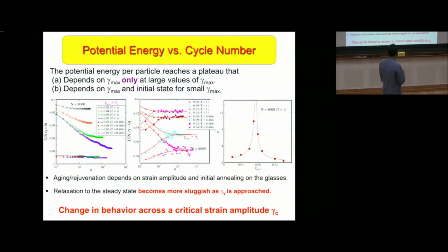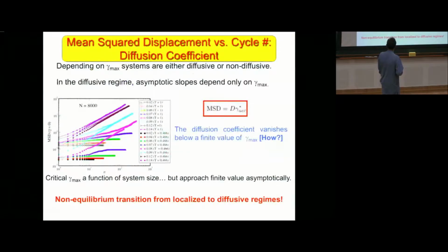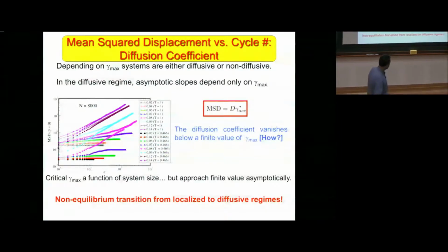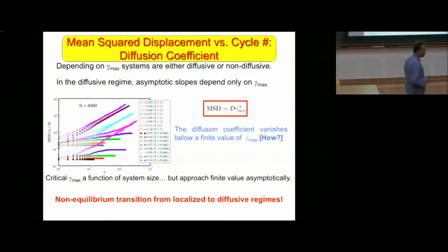And what you also see is the amount of time it takes for me to reach the asymptotic value is increasing, right, in one way. So it's increasing as I increase the strain here, and it's decreasing as I increase the strain here, strain amplitude. And that gives you a non-monotonic curve. And so the system is becoming very sluggish as you approach a critical strain value at which something dramatic happens, okay? So let me not dwell on this, but basically in the two regimes, yeah.